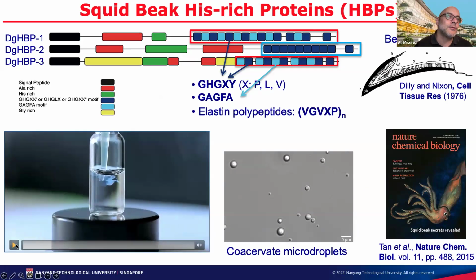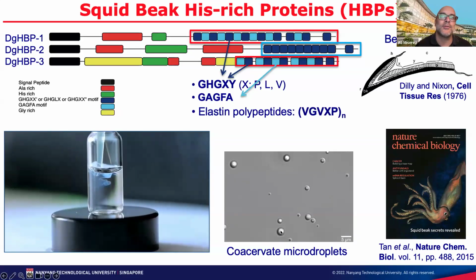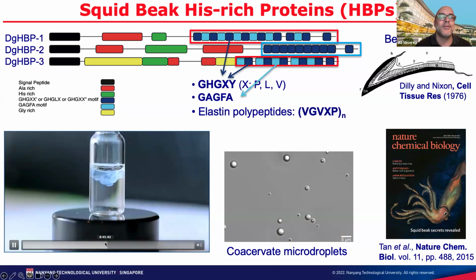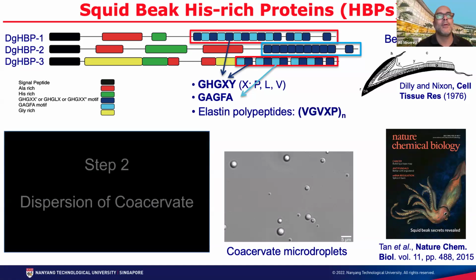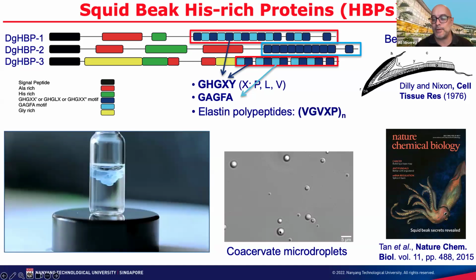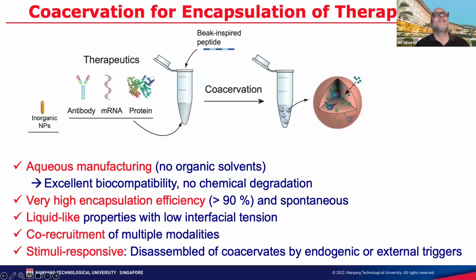if you have any macromolecule in solution here, somehow when you do this process of phase separation, a lot of them will actually get entrapped inside those droplets with very high efficiency, like up to 95%. And this happens in a few seconds, it's spontaneous. So it means you can encapsulate all sort of macromolecule, including therapeutic, inside the droplet. So this process of coacervation is very interesting for therapeutic because the whole process is done under aqueous condition. So there's no organic solvent.